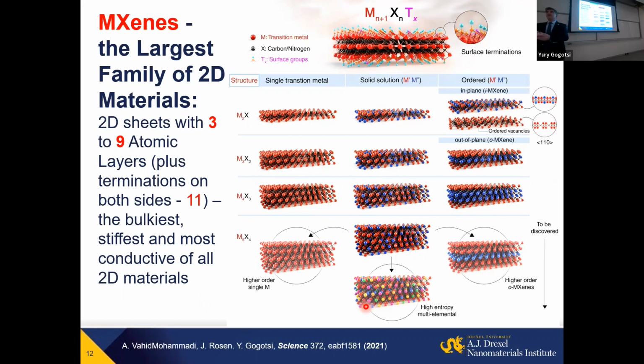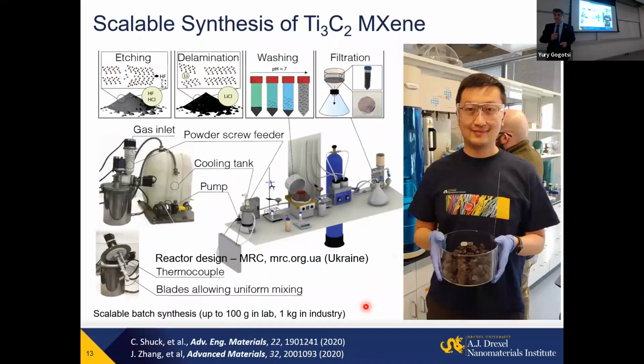But only about 50 have been experimentally produced so far, because someone needs to go to the lab, make a MAX precursor, make a MXene, characterize it, and so on. So there is plenty of room left for discovery for younger people in this room in that field. Now, we have this huge family of materials. But you know that probably at least 200 2D materials have already been experimentally reported, and more than 1,000 predicted, or 2,000, I believe, lately, if you count simple MXenes, have been predicted theoretically.